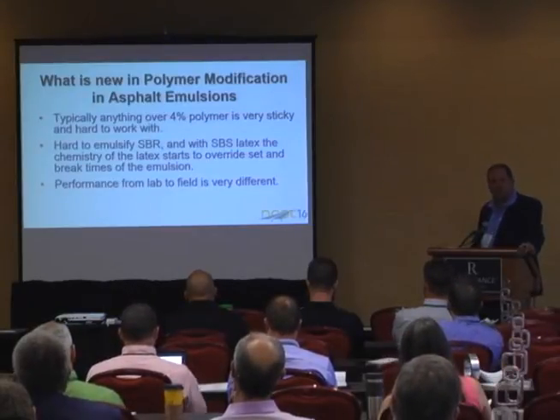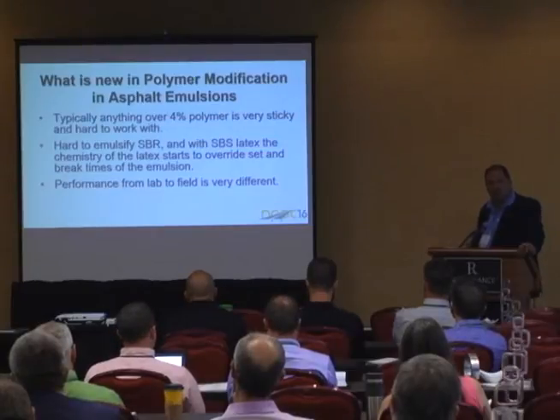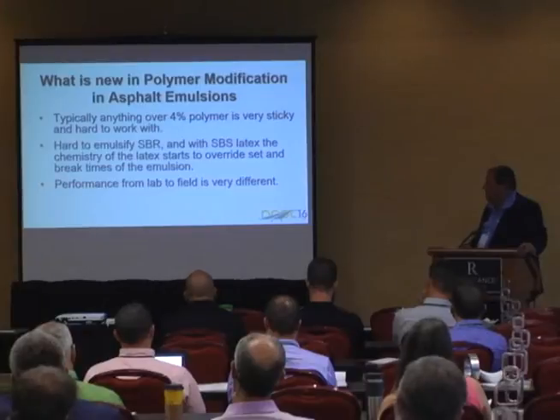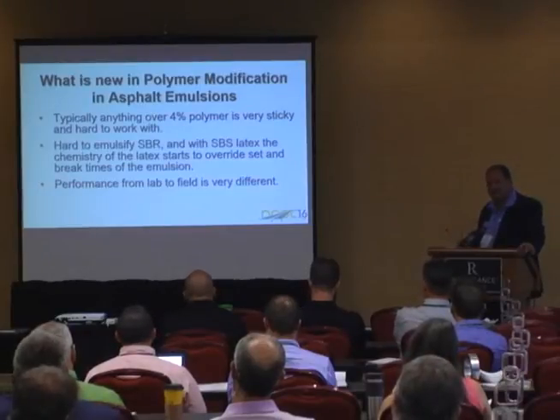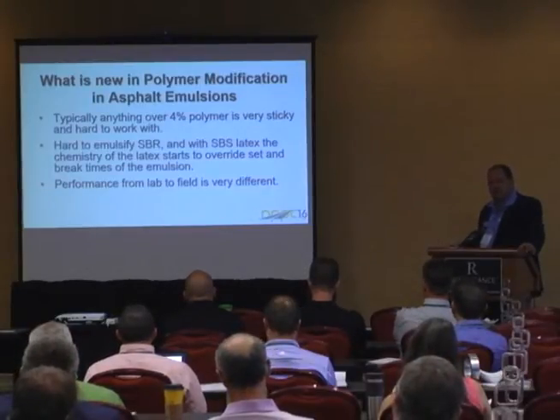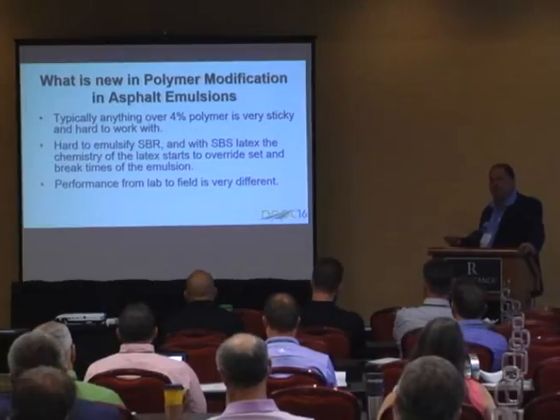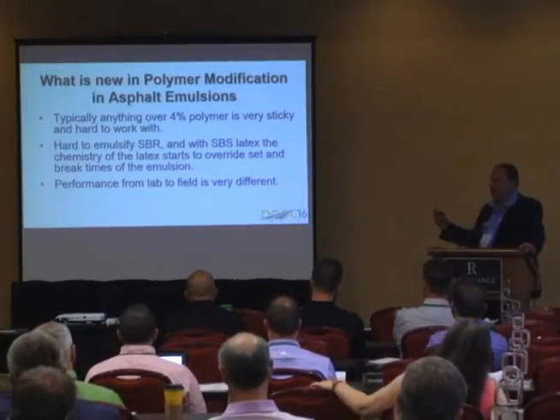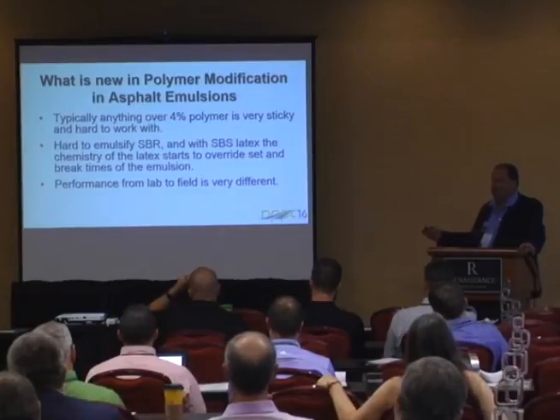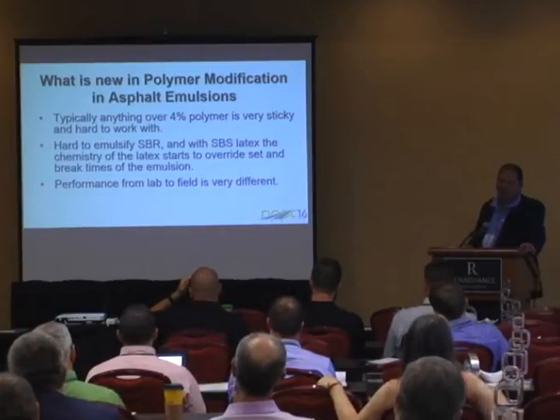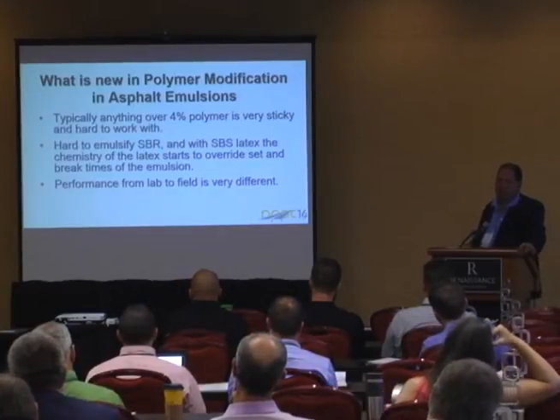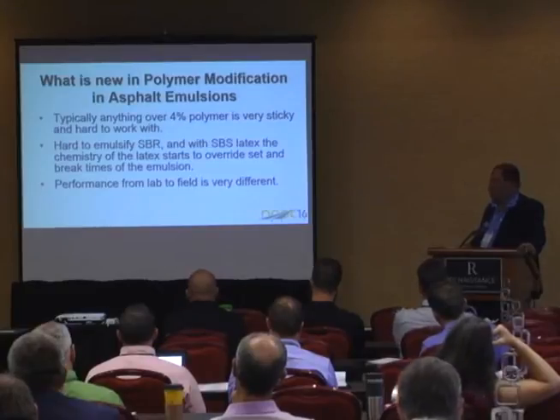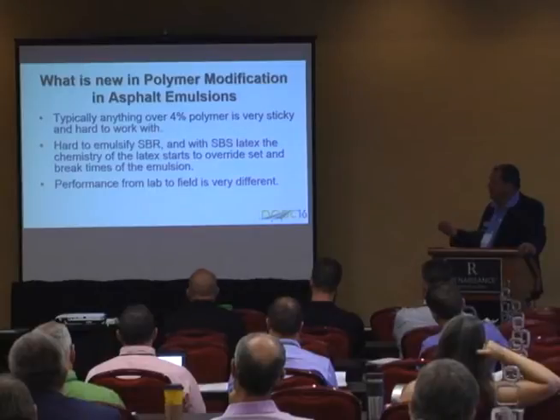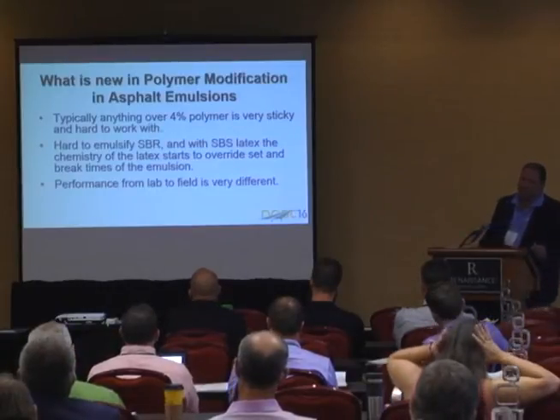Historically, some of the Novachip, Novabond, the polymer modifieds for the ultra-thin bonded wearing course, we're about 3% modification. SBS latexes are great, very effective, but once you start getting into 6% of that, or having to go to 8%, you start having the chemistries of those latex emulsions override the chemistries in the polymer modification. I should say, overrides the emulsion. And then you also have the performance from lab to field, very difficult.